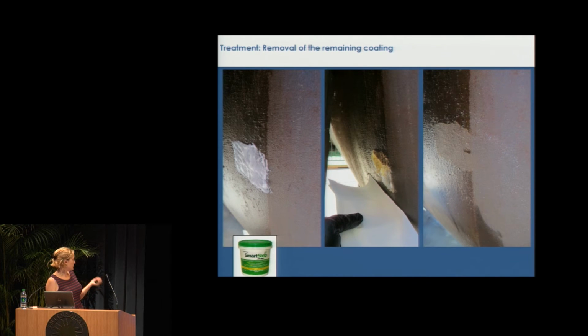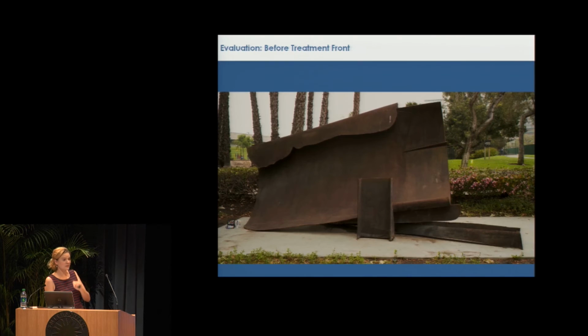We used about 2 of these buckets. We applied it, and then we rinsed it with hot water, and then we rinsed it with a power wash. And the good thing was that there was no difference between the blasting and what we took off. So you didn't have a difference in corrosion appearance. It was about the same appearance, which was great, because one of my concerns with the dry ice cleaning was that I would have streaks of where I blasted or patterns in the blasting, but there was none of that. So I was very happy about that.